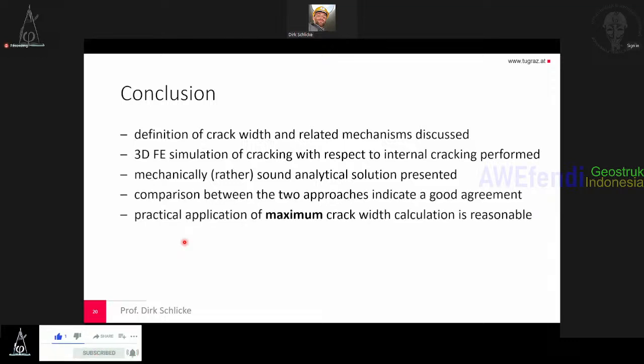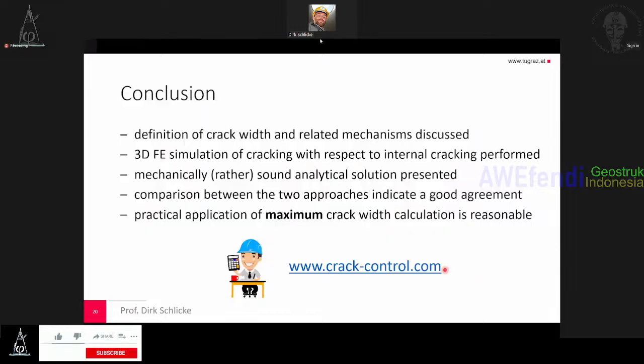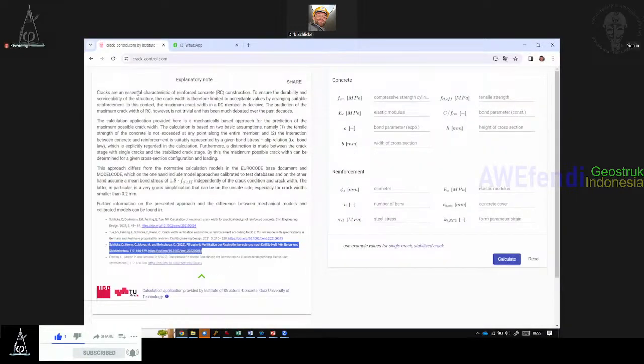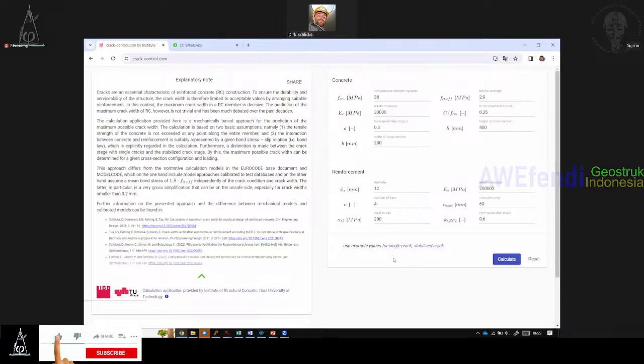We compared the two approaches. They indicated a good agreement, and the practical application of maximum crack width calculation is therefore reasonable. Overall, you can go and use this already on a homepage. It's called crackcontrol.com. Here's some explanatory note. I will not go through this now due to time reasons, but what you can do, you can fill your data in here for the concrete compressive strength, tensile strength, elastic modulus, some bond parameters, the cross-sectional area, reinforcement,